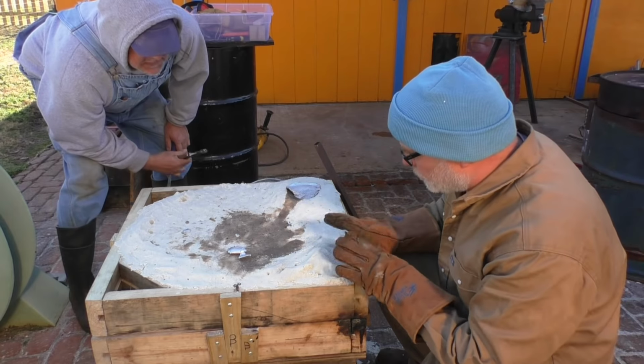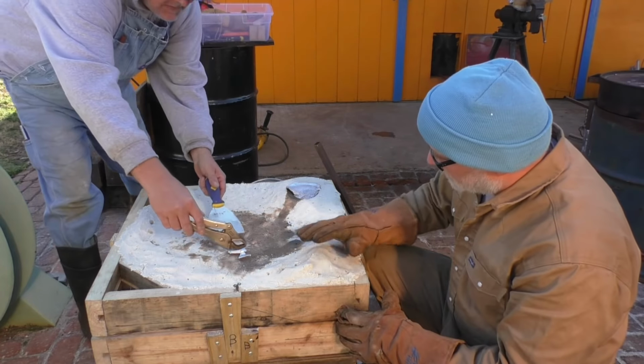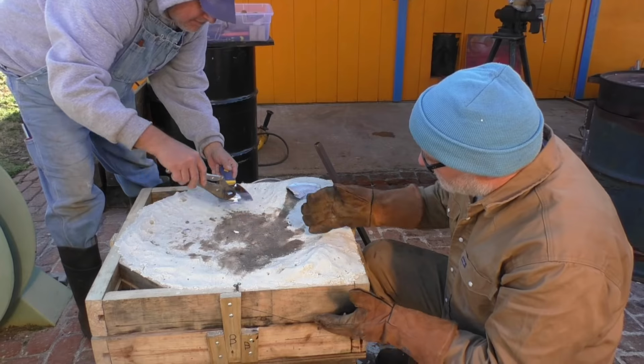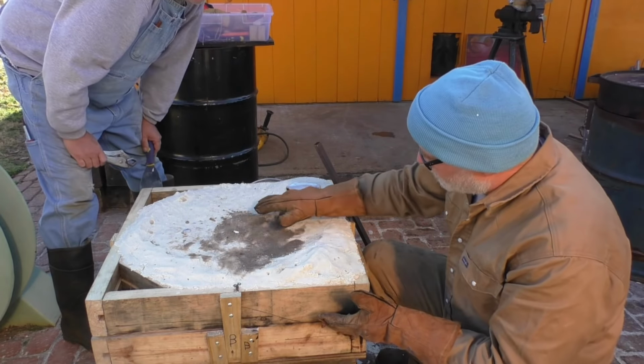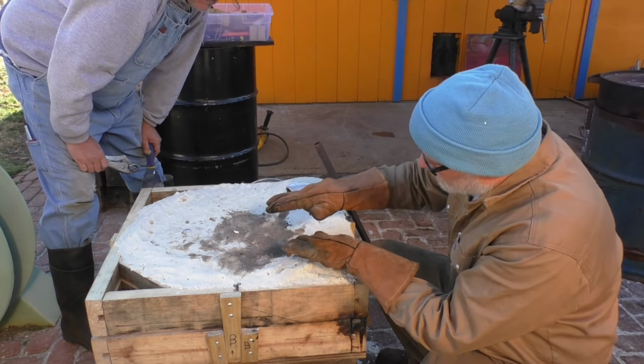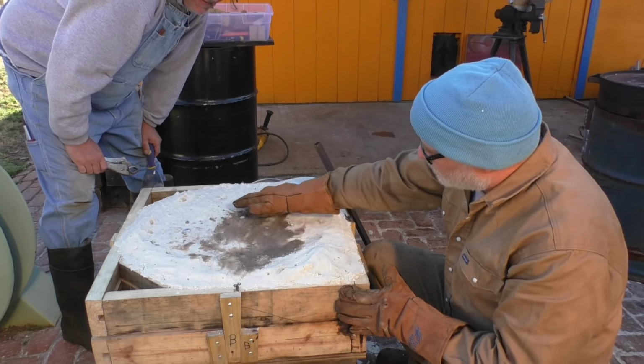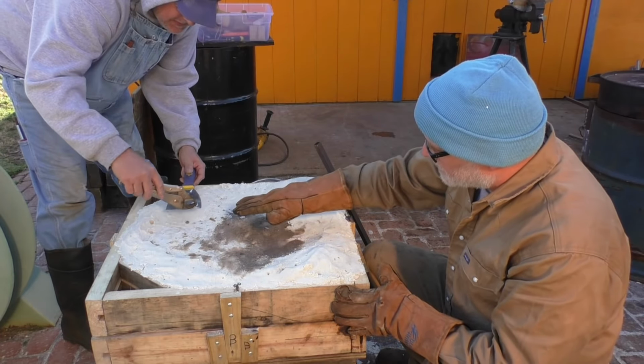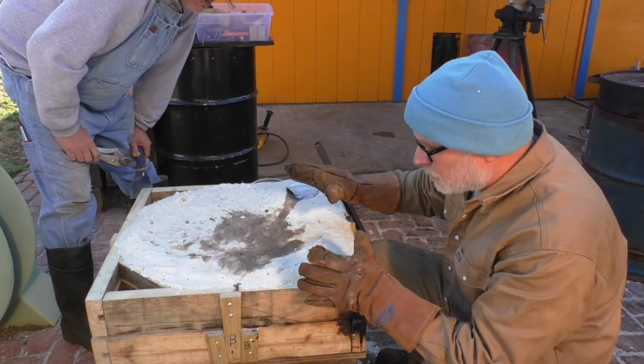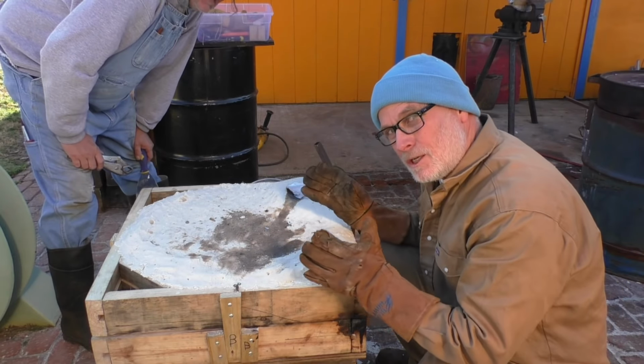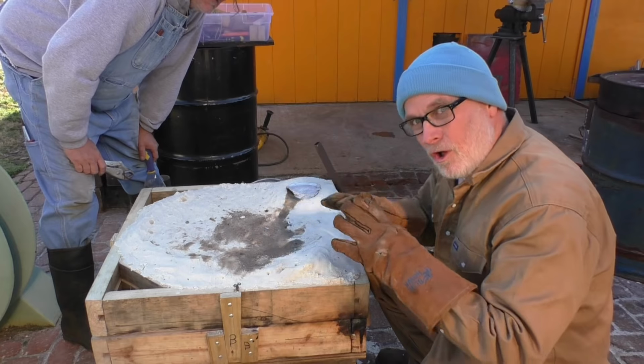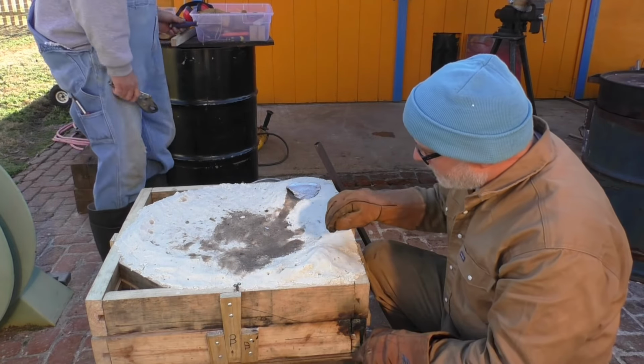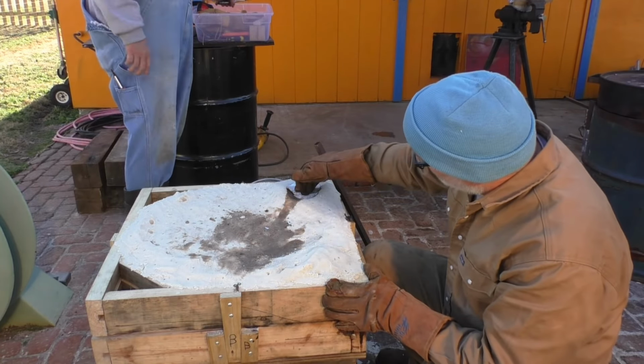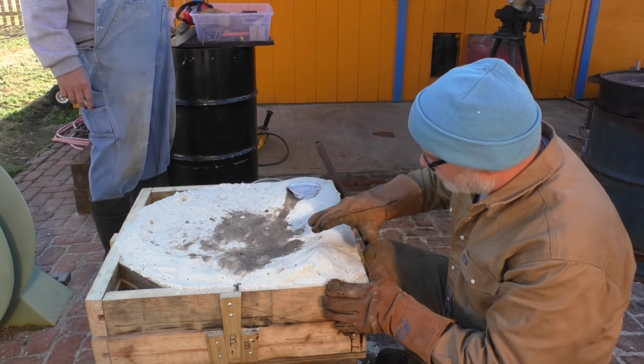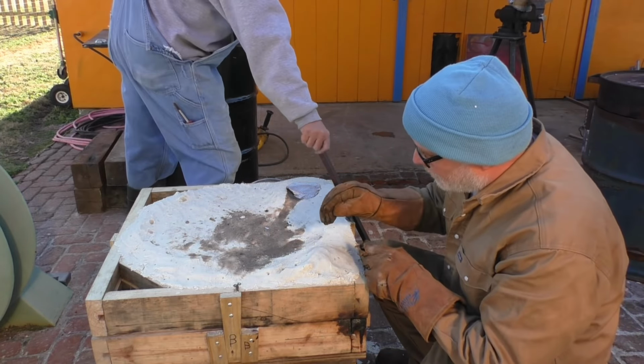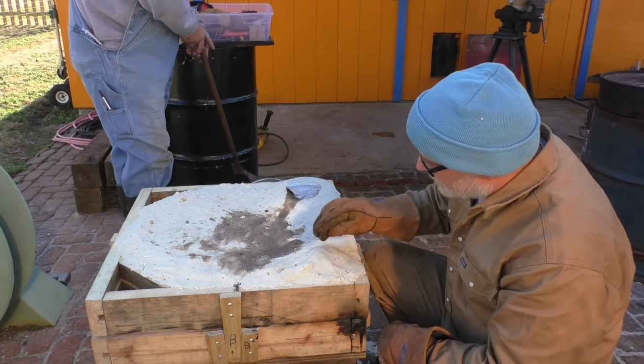The trick here is the riser. The riser is this big massive part that comes all the way up to here. And after the part is filled with aluminum, some of that air actually pushes through the sand, so it'll fill even that bulbous part out here in the center by just pushing air through the sand. Once that's all done, though, it's going to start cooling, and when aluminum cools, it's going to shrink 2%. And that's just a rule. All metal shrinks about 2%. But what happens, the last thing, while this is filling up and making this pool that stays in here, this riser is filling up. So the very hot metal at the last of the pour goes into this riser.